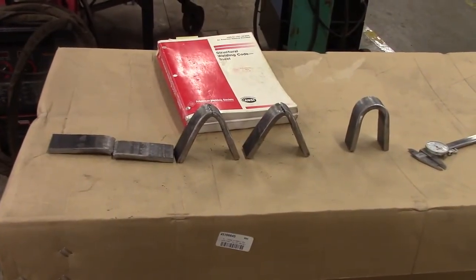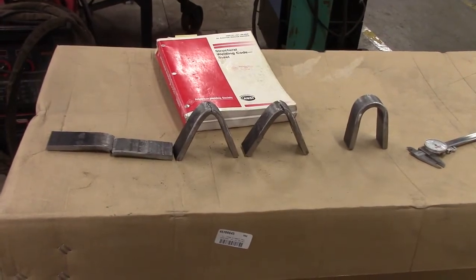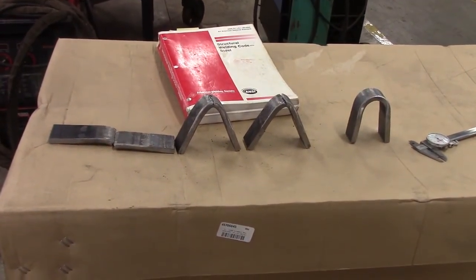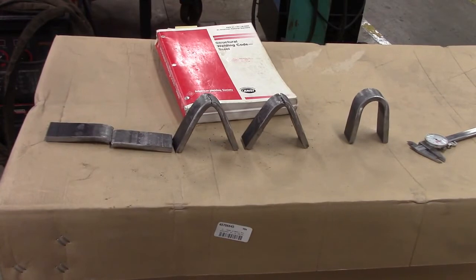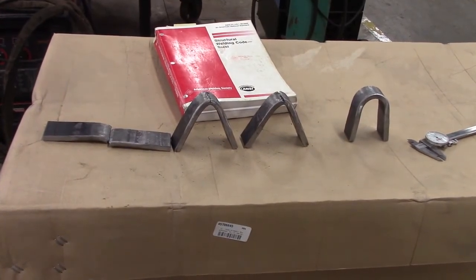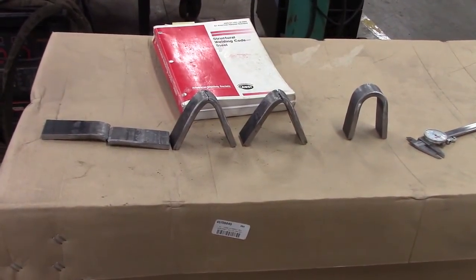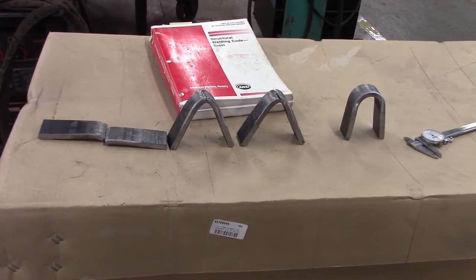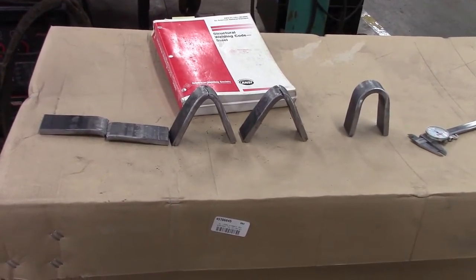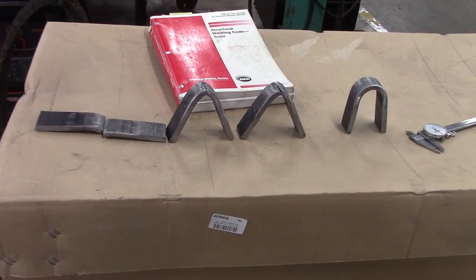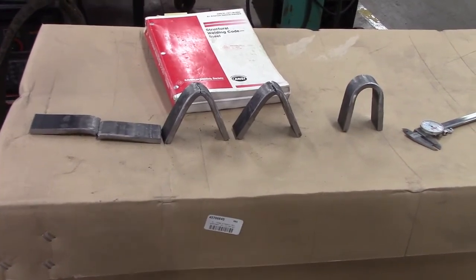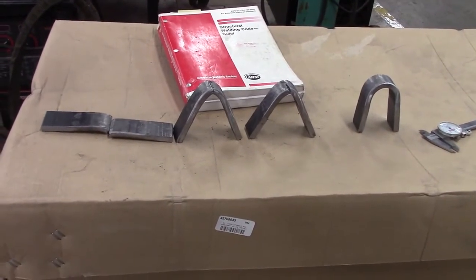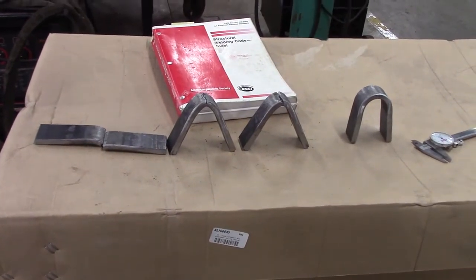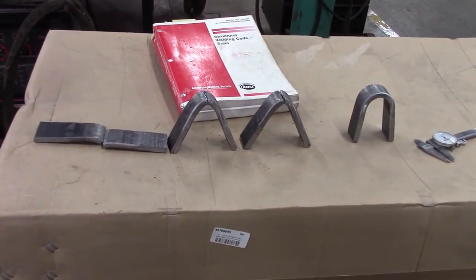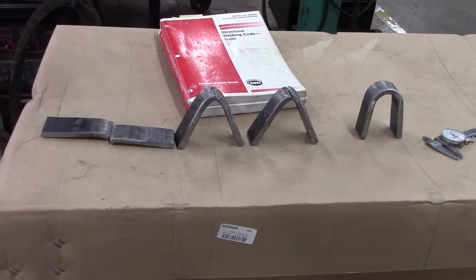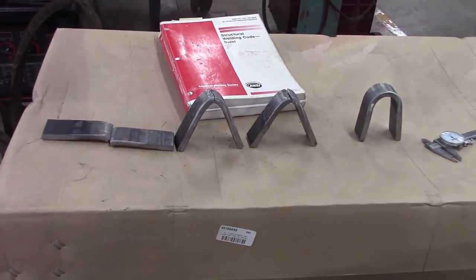Alright, here's our 4 bends, and you can tell that we've got massive failure on 3 of them, which if you have massive failure on any of them, you failed the test. Now there's a couple reasons why. First, we're going to look at the breaks, and this just shows you that you can have a perfect looking weld not bend, but it's obvious when you look at the break why these broke off. So let's take a look at the breaks.